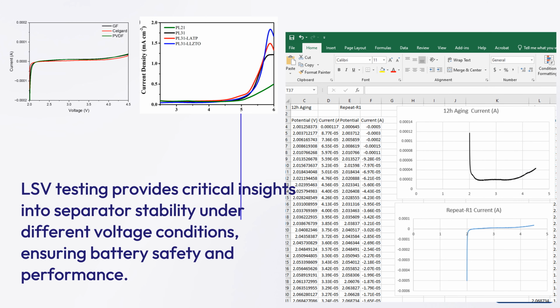So here is the real data. For example, when you test the cell, the LSV test in the beginning will give you a curve like this, the black curve on the axis. The current drops from OCV, open circuit potential, to close to 0, then continues with a slight increase in the current. There is no big spike.